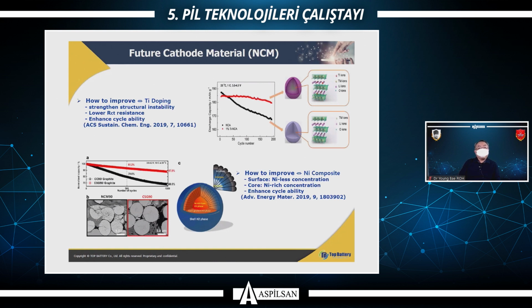So how can we improve the high nickel cathode material performance? First, we can think of the doping process. As I mentioned before, titanium is good for strengthening the structural stability due to the strong bonding structure with oxygen, and lowering the charge transfer resistance, and it leads to enhanced cyclability.